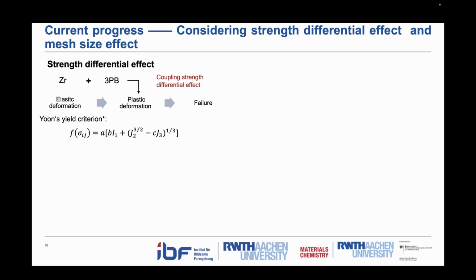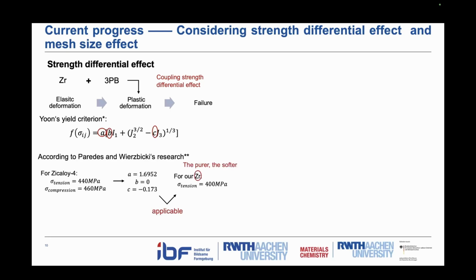So we have chosen the yield criterion, and there are 3 parameters A, B, C for us to calibrate. And we check our experimental result, and we also refer to the work of other people, and then we finally determine a group of ABC values.